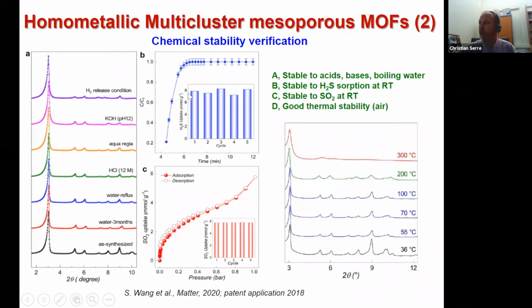And you could see that after 5 cycles of adsorption-desorption, there was no modification of the sorption capacity of the material. Also, another point for some applications is the thermal stability. So this MOF is a complex material with Zr12 and Zr6 clusters, and it's also a 2D structure. Sometimes 2D structures are less stable than 3D.